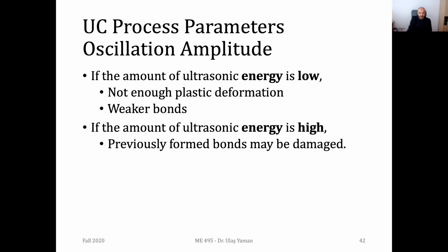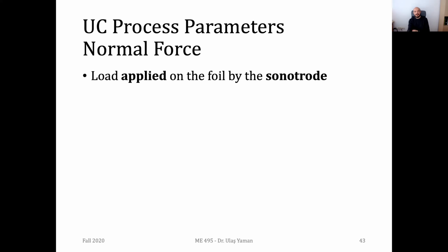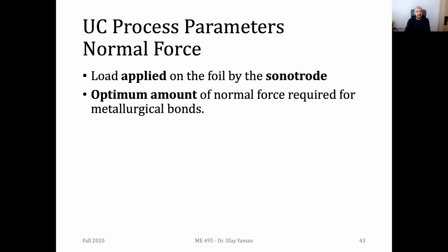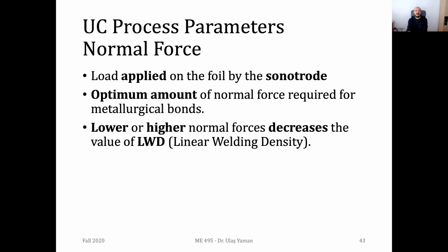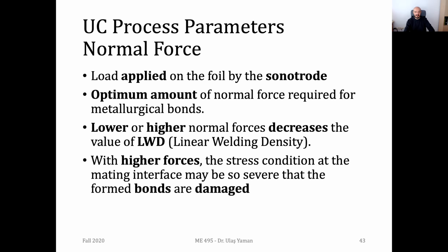These are the same things we discussed. Now let's have a look at the importance of the normal force. Obviously, it's the load we are applying on the moving, rotating sonotrode, and the optimum value of this force is highly important to have metallurgical bonds. We shouldn't have too high or too low a force. As your friend pointed out, if you have lower or higher forces, then the quality of your bonding or the linear welding density will be low compared to the optimum value. If you have higher forces, then the previous layers or the top surface will be deformed and the upcoming interfaces will be affected.